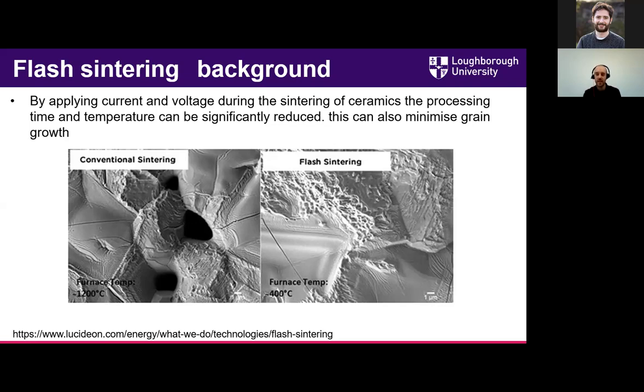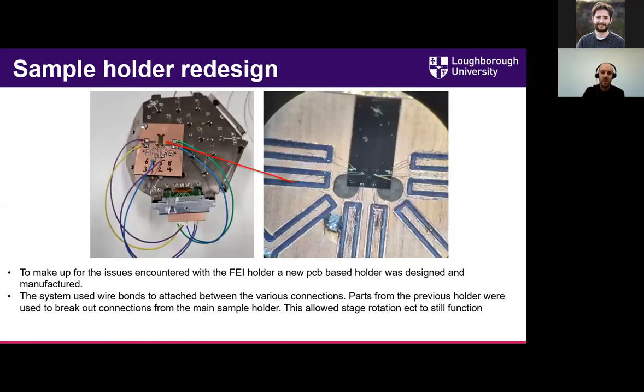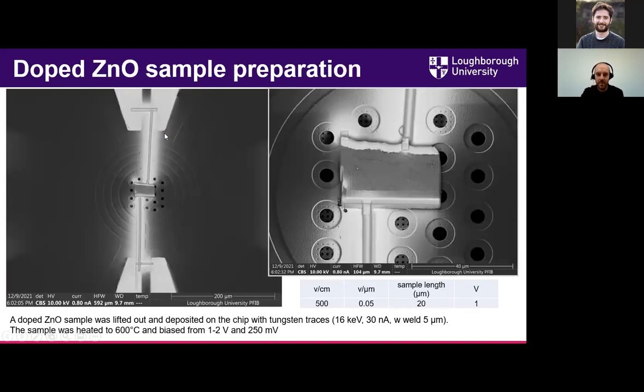And in that case, the sample will sinter within a few minutes without having to go to that really high temperature. This is super exciting for ceramicists, as it allows you to sinter samples at lower temperatures much quicker, and sometimes it results in a smaller final grain size. So what we wanted to do was do this in situ. So here we have an in situ stage with the biasing setup. We've built a little holder for that.